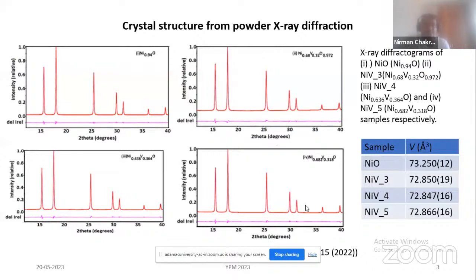The second reason is that from our previous studies, we found that if we dope a material with a metal atom having a smaller ionic radius, it leads to a reduction in the unit cell volume. That makes an increase in the surface density of active sites, which improves their surface performance. For that purpose, we did vanadium doping in our nickel oxide system.